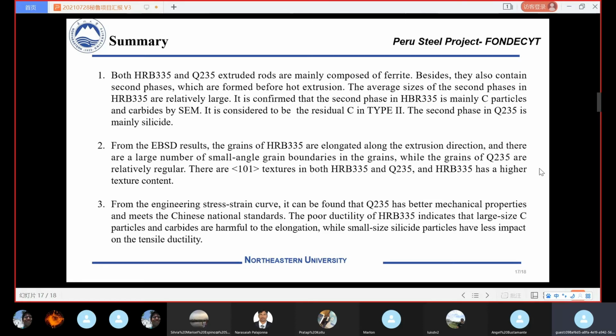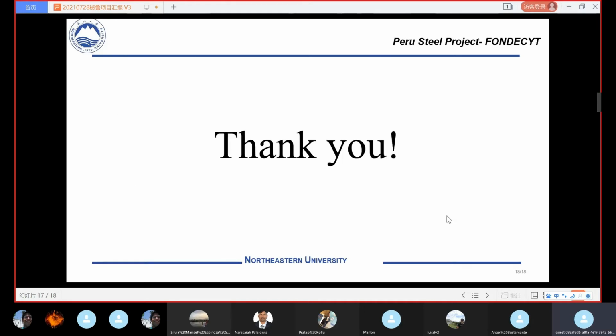From the engineering stress strain curve, it can be found that Q235 has better mechanical properties and meets the Chinese national standards. The poor ductility of the HRB335 indicates that large-size carbon particles and carbides are harmful to the elongation, while small-size silicide particles have less impact on the tensile ductility. Okay, thank you very much for your attention.